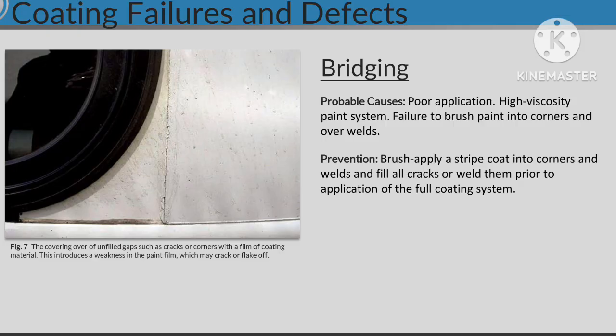Bridging. Probable causes: poor application, high viscosity paint system, and failure to brush paint into corners and over welds. Prevention: brush apply a stripe coat into corners and welds, and fill all cracks or weld them prior to application of the full coat.